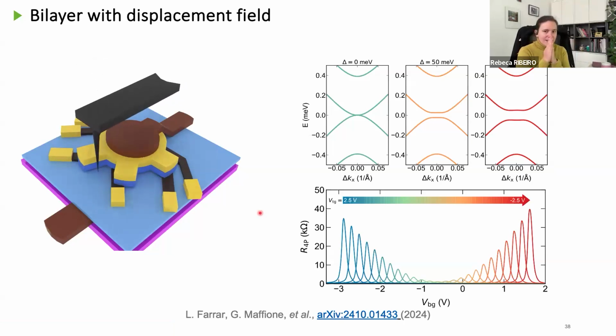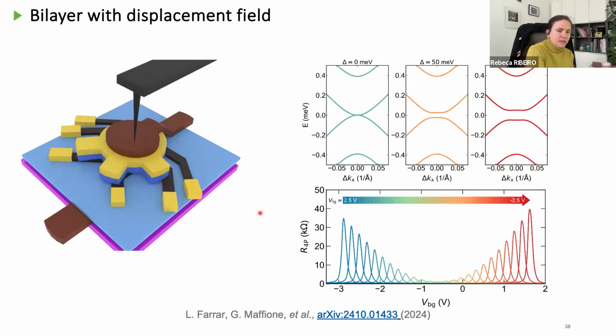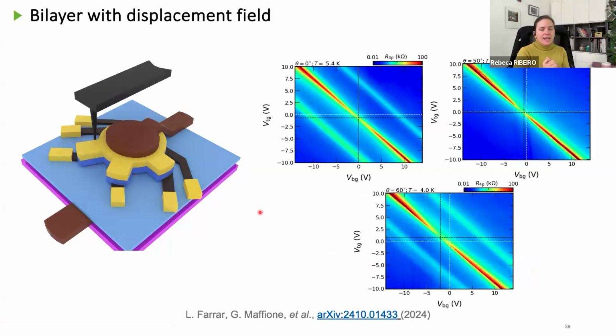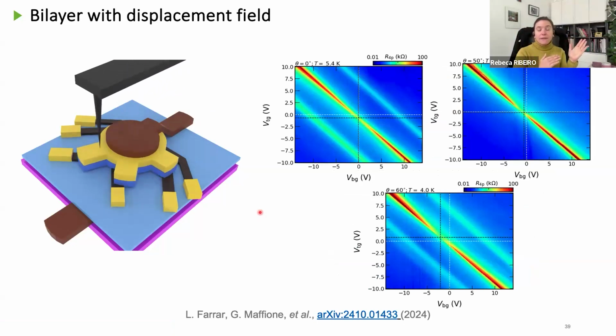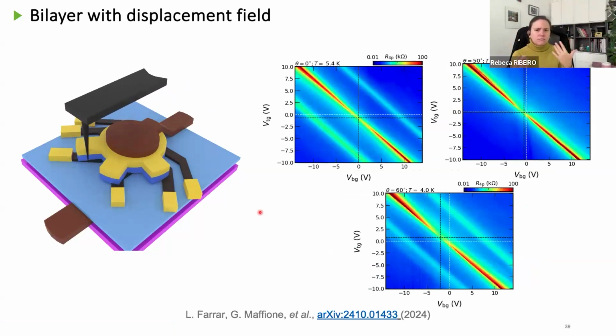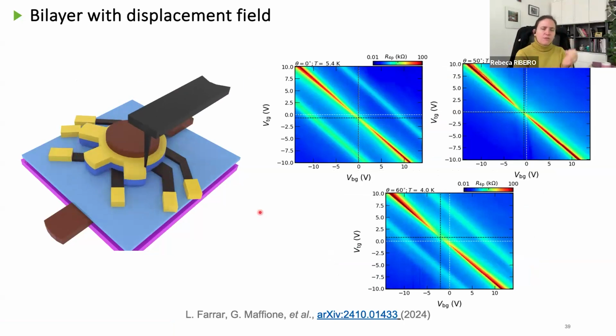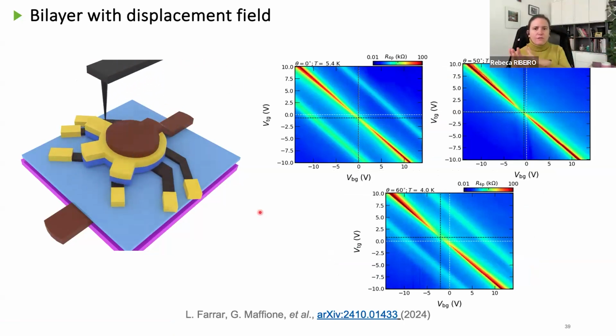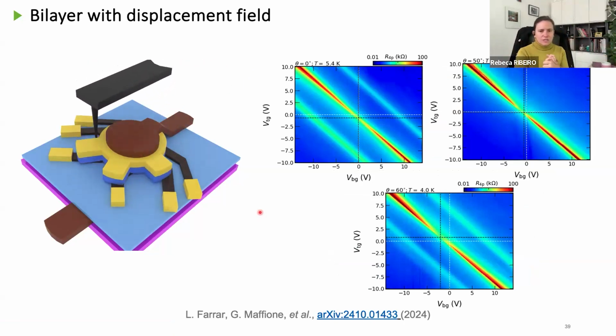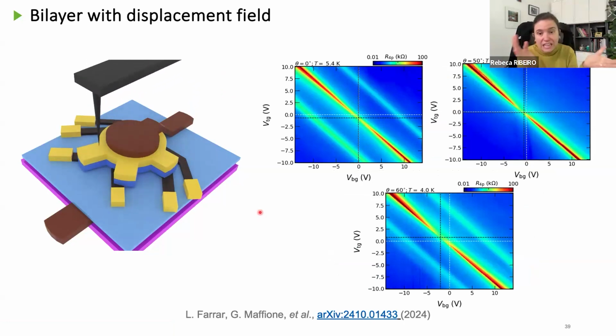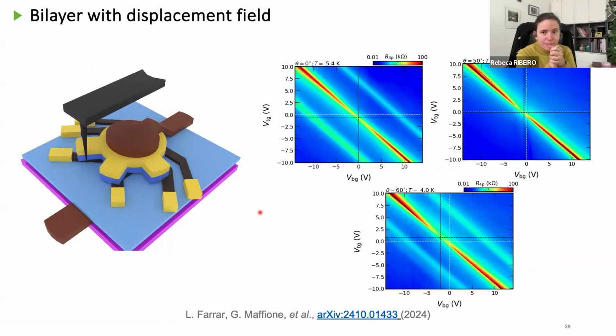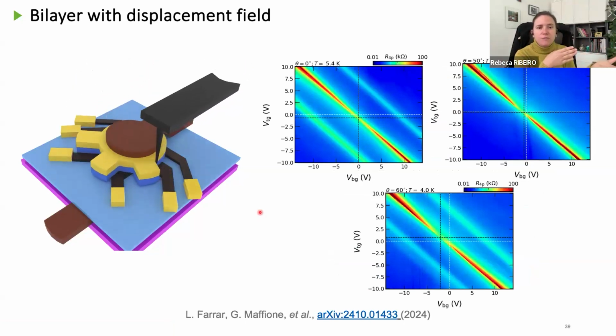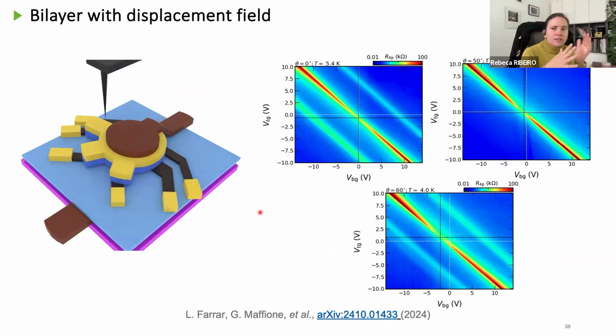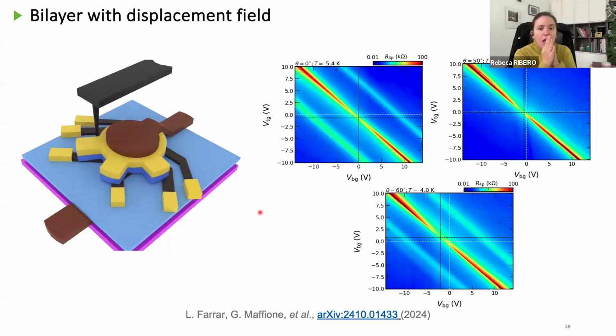So, okay, we can change the gate in both senses, and we can also change the alignment. So now we can do a little bit the same that we did before. We compare 0 degrees, 50 degrees, and 60 degrees of alignment. And to be honest, they don't seem very different, much more than what we saw before. Some peaks are higher, some peaks are lower.